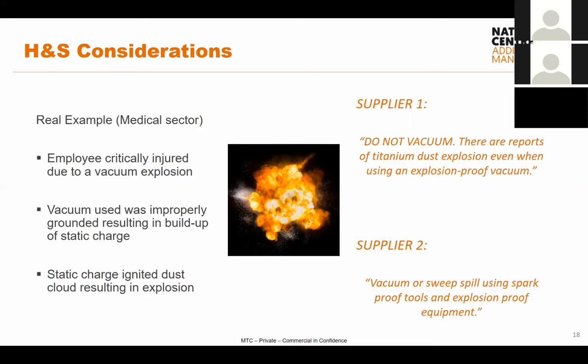so clearly one person getting injured is not ideal, obviously not. But when it comes to explosions like that, sometimes it's not the primary explosion that's the worst thing. It's often the secondary explosion. Why that's so important is, if you get one explosion, if you have any dust around your facility that hasn't been cleaned well, that can get unsettled and then in itself can cause a secondary explosion, which can be much worse because there can be a lot of it. So clearly housekeeping is a major issue. You should keep on top of it.